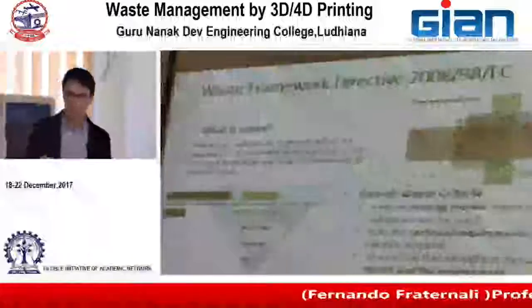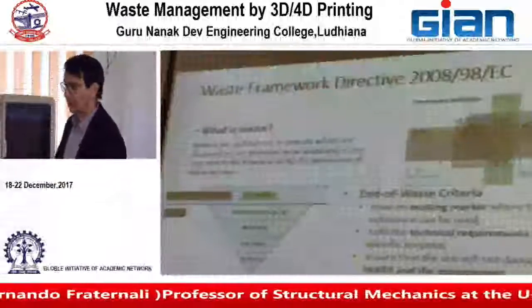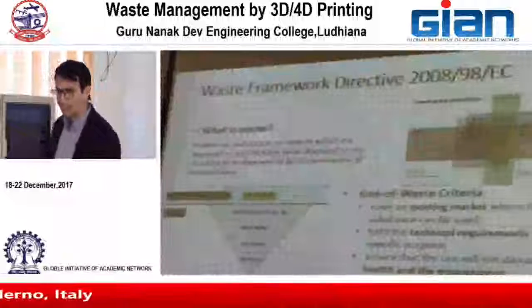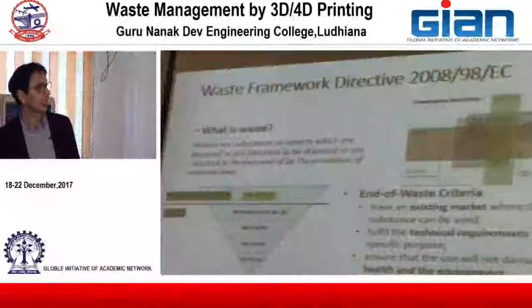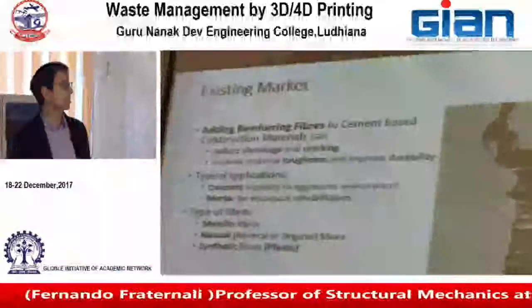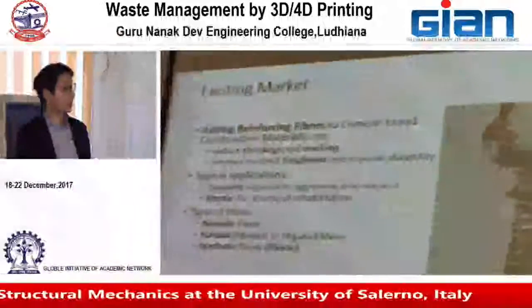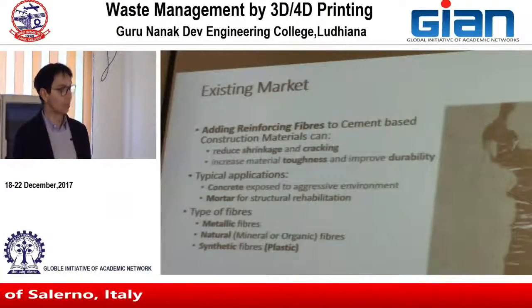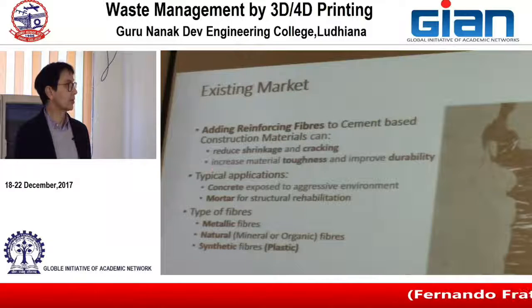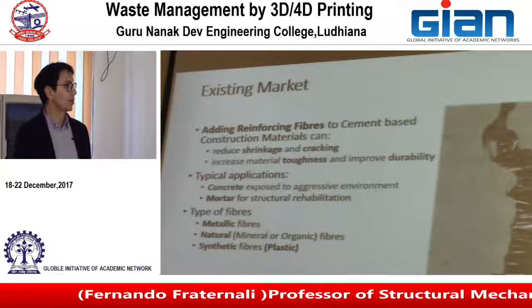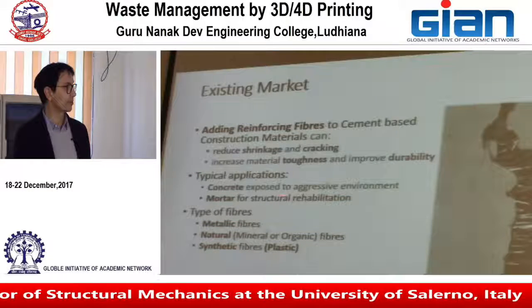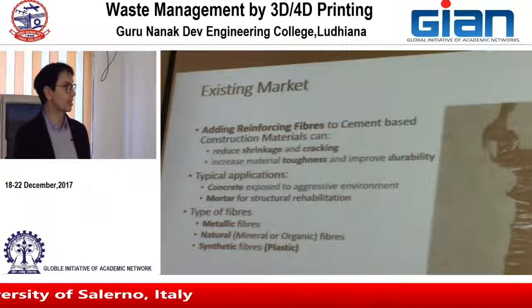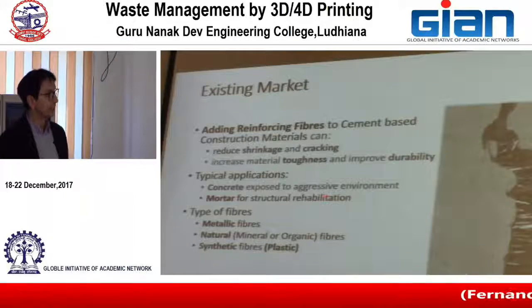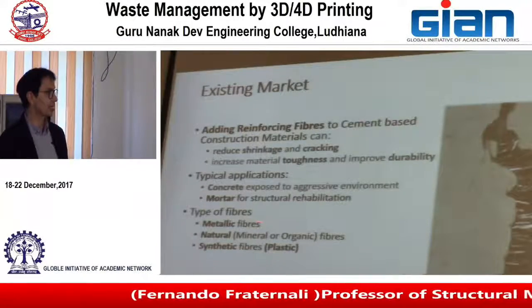And because, as we noticed before, the nylon has some hygroscopicity issues, which makes the material more well suited to mortars than concretes. Indeed, this was the case. So there is the existing market of reinforcement of concrete and mortars with plastic fibers, which encompasses applications relative to concrete exposed to aggressive environments, and mortars for structural rehabilitation. The fibers can be metallic, natural, or plastic.